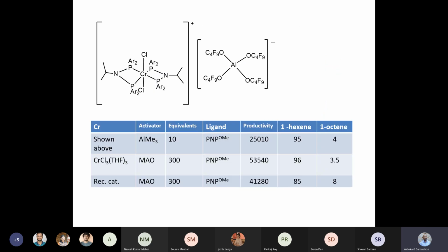So here is a paper where they've used 10 equivalents of AlMe3 as an activating agent, and you look at the difference between MAO and what trimethyl aluminum can do. The productivity or the turnover frequency of the same catalyst activated by AlMe3 is 25,010. Whereas if I use MAO in the reaction, you get 53,540. The recycled catalyst in these cases